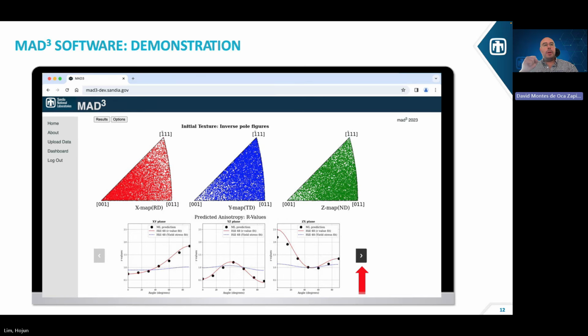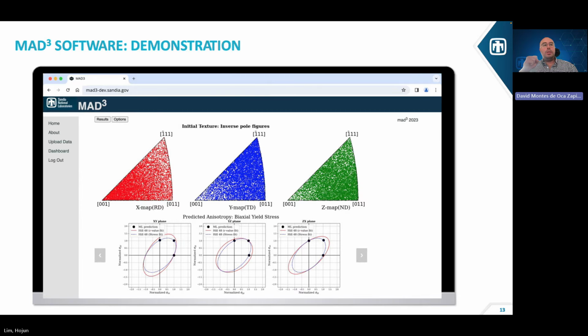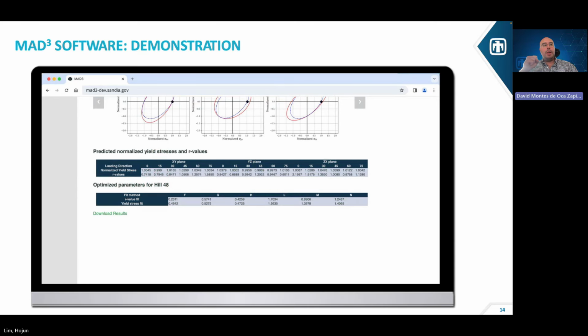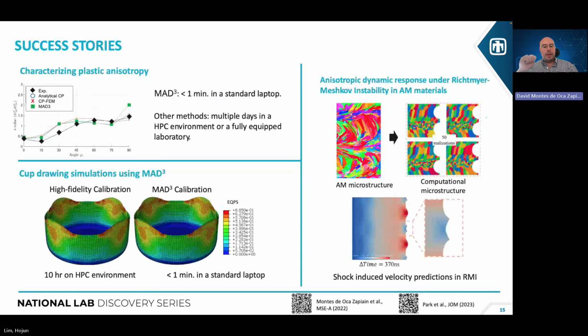You also get information about the thinning ratios or R values. And you also get information about the yield surface. Most importantly, after all this, you also get information about the calibrated parameters. You see, in this case, we selected Hill's 48, which is one of the most commonly used. And we obtained those 6 values essentially with the click of a button, using a standard laptop on an easy to use GUI that is deployed via the web, so you don't need to worry about installation. So naturally, as you can see, MAD³ provides the capability to calibrate complex deformation models.